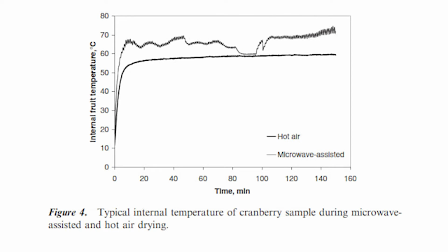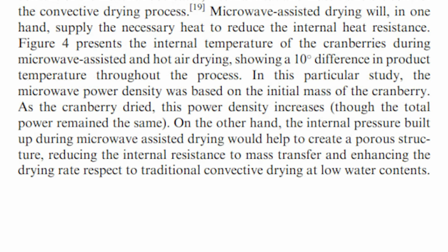Figure 4 presents the internal temperature of the cranberries during microwave-assisted and hot air drying, showing a 10° difference in product temperature throughout the process. In this particular study, the microwave power density was based on the initial mass of the cranberry. As the cranberry dried, the power density increased, though the total power remained the same. On the other hand, the internal pressure built up during microwave-assisted drying would help to create a porous structure, reducing the internal resistance to mass transfer and enhancing the drying rate with respect to traditional convection drying at low water contents.